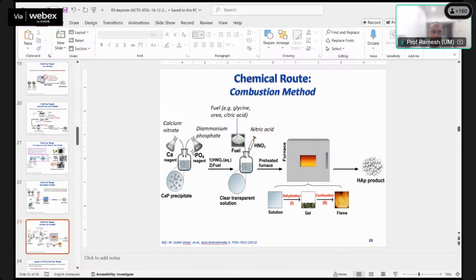Of course at a certain ratio, you've got to keep the ratio of Ca to P at 1.67. So you need to work out the amount of ammonium phosphate versus the calcium nitrate. You mix them, and thereafter you put it on a hot plate, normally in a stirring condition, and you pump in nitric acid or glycine as a fuel. As the product dries up, you will get a combustion, and after the combustion, the product that is produced will be the HA product. But it's difficult to control in terms of properties and yield.